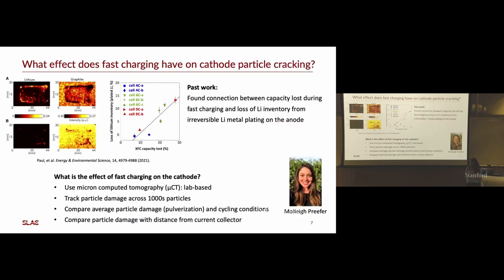Okay, so fast charging. Our past work, in summary, is right here. We mapped lithium, we mapped the state of graphite, and we also mapped two different batteries. Actually, we mapped a whole bunch of batteries, I think 9 batteries, at different states of charge, and we found a connection between the amount of capacity lost during fast charging and the amount of lithium plating that we have. And so there's a loss of lithium inventory from lithium plating, and that was a linear correlation with the capacity that we lost during fast charging.